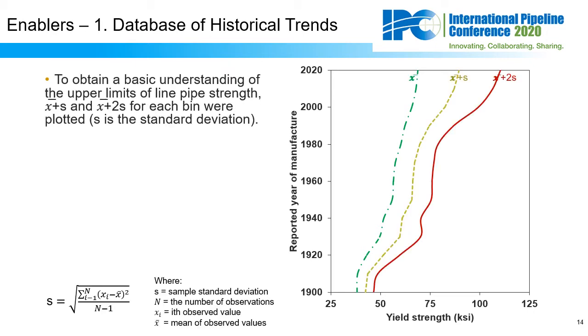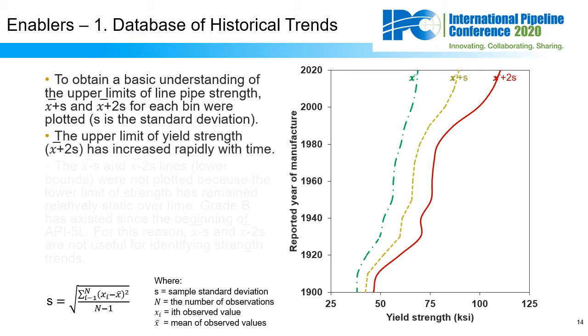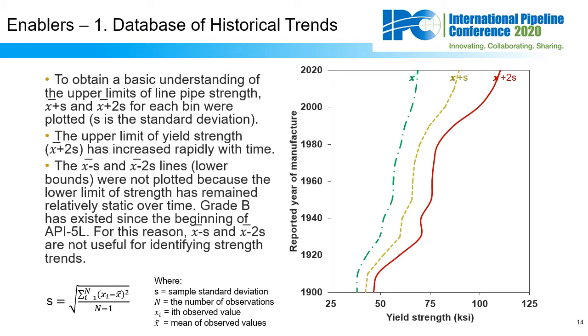Now we also wanted to get an idea of how the spread in the data changed over time. So the single standard deviation and the 2 standard deviation were added to the mean data and plotted as well. And the results here show, as you would expect, that the spread of data increased over time. And the distribution started out with a very narrow spread and gradually widened. And for yield strength, this widening was because additional grades of higher strength steel were introduced by API 5L. But the lower grades were still being produced as well.